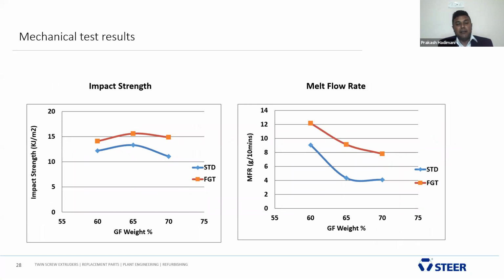Okay, impact strength, with the addition of glass fiber, the viscosity increases. Yes, obviously there is a tendency to reduce the impact strength, but up to 65, both are in a good condition so that at least you can get 15 kJ/m2. That is what the industry requires, 15. If you are looking for still further, then you need to modify your formulations to reach that level. But in the standard, it came down drastically, to around 12 kJ/m2. The melt flow index reduced because of the addition of glass fiber. When you add it, the viscosity increases and melt flow rate drops down.